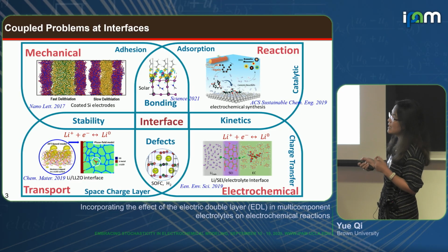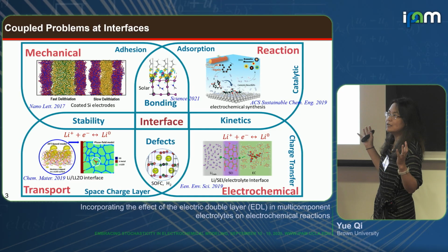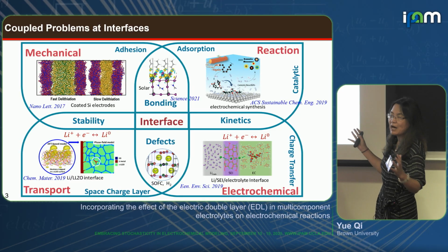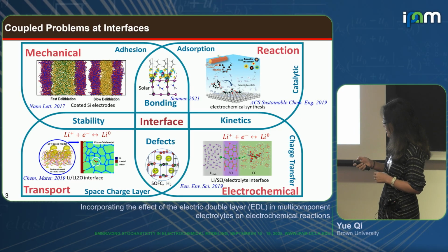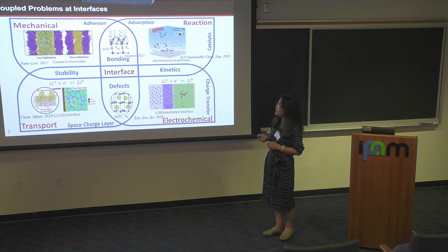So in my early work, when I thought about interfaces, I often described how lithium goes into an electrode and out, and how that changes the volume, and that causes some failures. This is delithiating silicon. This is delithiating fast. This is delithiating slowly. So we got more lithium out of this, but even then, we can see some interface delamination.